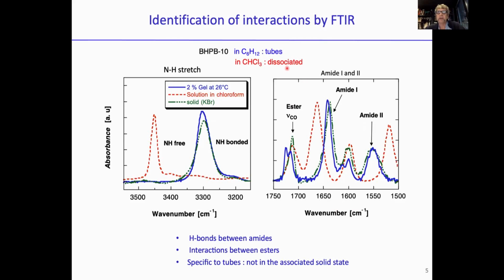You can compare to convince yourself what happens in chloroform. In chloroform, all the molecules are dissociated, there is no association in the solvent, the NH are free, and you can see the shift for the amide 1 and amide 2. And if you compare with the neat solid, the powder, this is the green curve here. You see that in the powder, of course, all the amides are held together by H bonds. And what is quite strange is that in the same area, you have the signal for the ester, the CO stretching of the ester.